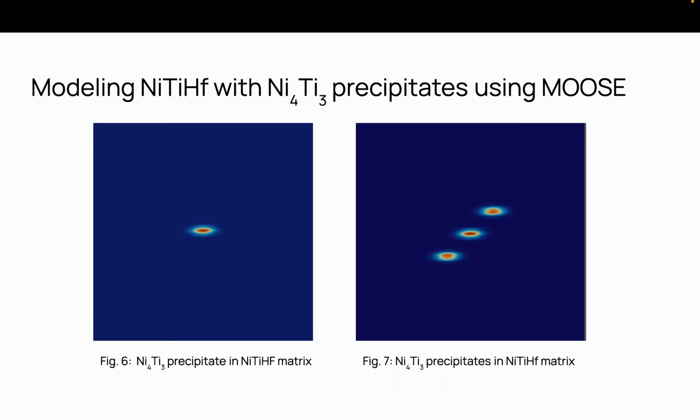After implementing the eigenstrain, the elasticity, and the elasticity tensor, there was proper shape and size. Here are the precipitates being generated currently. These precipitates have been generated from concentration without orientation variance, which is why there is no tilt. This lays the groundwork for the future because once variance can be properly implemented, the precipitates and matrix can be investigated further to see how spacing, number of precipitates, and volume fraction play a role in solid phase transformations, as well as to explore the impact of key crystallographic orientations.